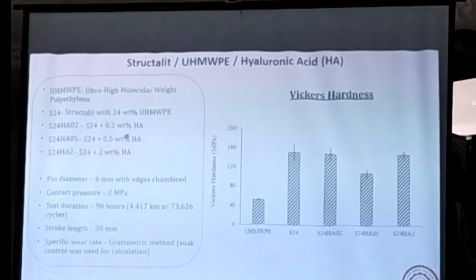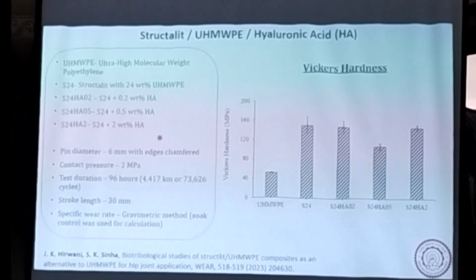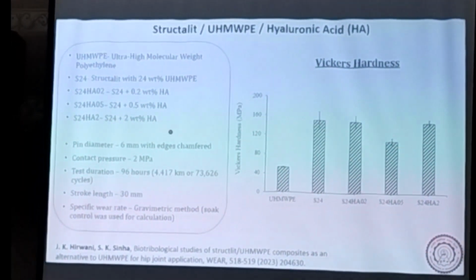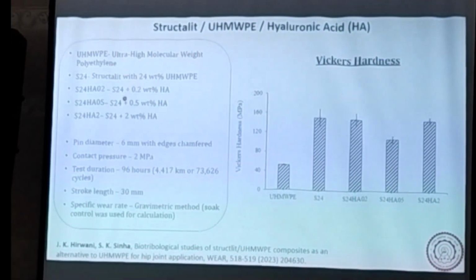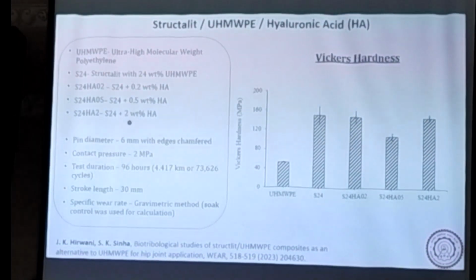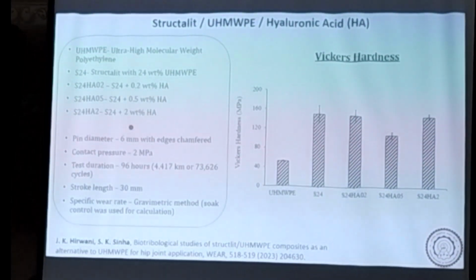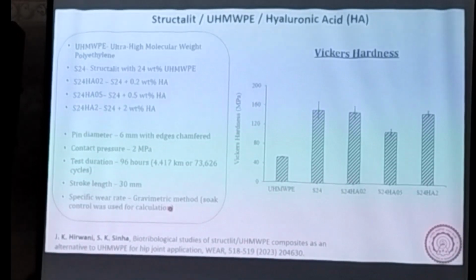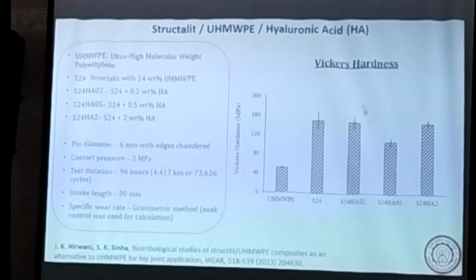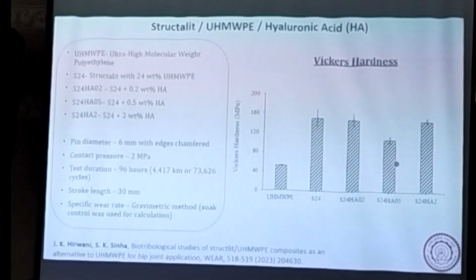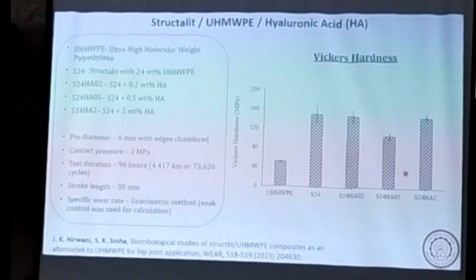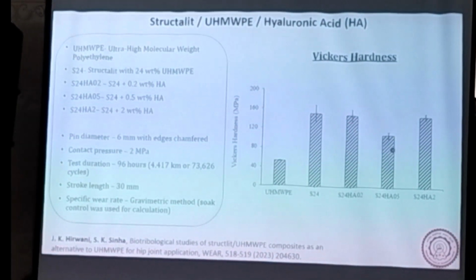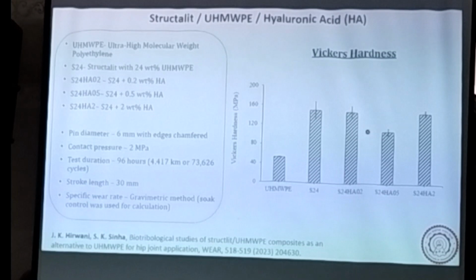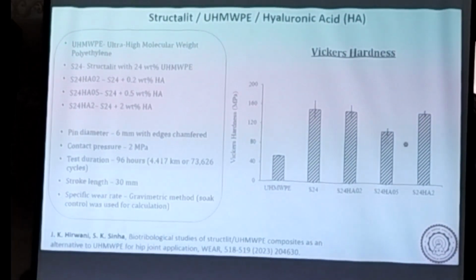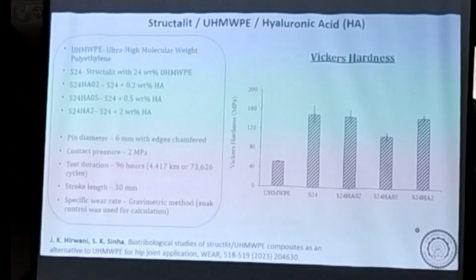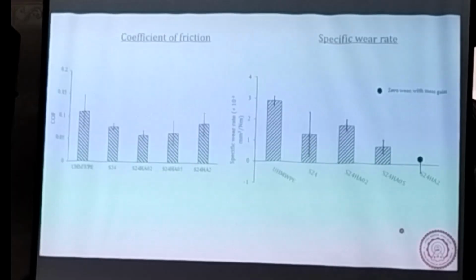So after adding HA, hyaluronic acid, which is a bio-lubricant, we have tried 0.2%, 0.5% and 2% just to see what kind of improvement in tribology we can see. And this gives us hardness results, and generally we don't see any kind of trend, but we can say a slight reduction in the hardness because of the lubricant.